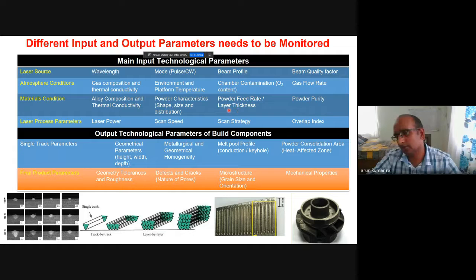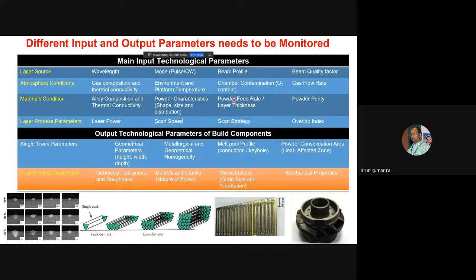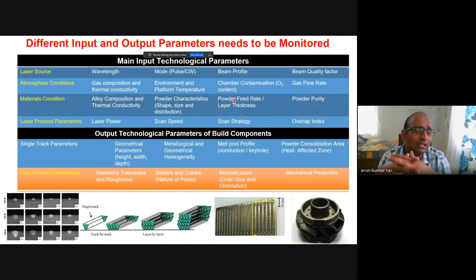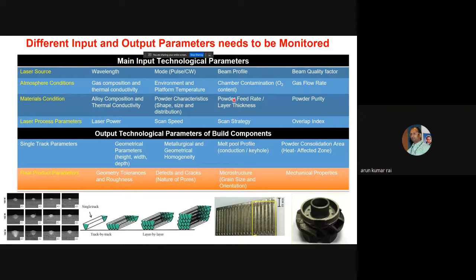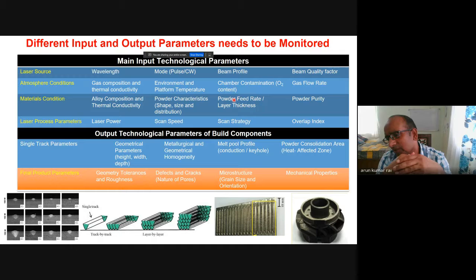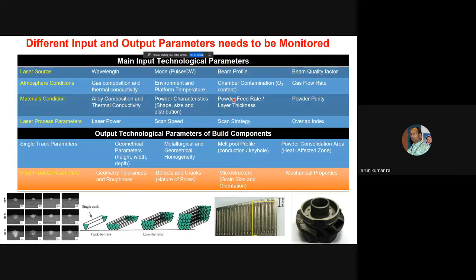Then powder feed rate and layer thickness. Already I have told you. In direct energy deposition, you are coaxially feeding the powder along with the laser. So you cannot feed either a very high amount of powder or a very low amount of powder, because both are going to create a problem. If powder is very less and your energy is constant, it will create a turbulent melt pool, which will flow and not form the proper shape. Okay. Or if you are feeding a very high amount of powder, then unmelted powder can be left, and that leads to porosity formation.